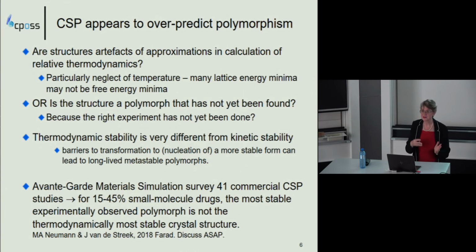It can also be very difficult to nucleate, for the first time, a difficult-to-nucleate crystal structure. So there can be problems of this apparently stable structure actually being metastable because it has not had the opportunity to transform, or been seen to transform despite all the experiments they've done, because they haven't nucleated the other form yet. So the main commercial company that does crystal structure prediction calculations for industry, Avant-Garde Materials Simulation, in the